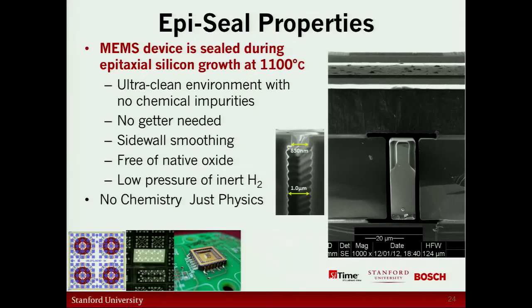The resulting technology has a lot of properties that we wanted, in that there was low pressure and a pretty clean environment. We thought that would give us a better shot at a stable resonator. It did some things that we didn't understand at the time, but have turned out to be really important. The sealing step takes place at 1100 degrees C and takes a half hour to an hour. So there's a very high temperature bakeout of the MEMS device during that process. It's unlike any bakeout ever seen anywhere else in the MEMS community.